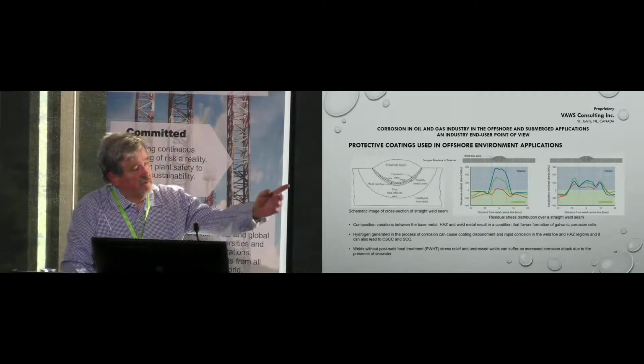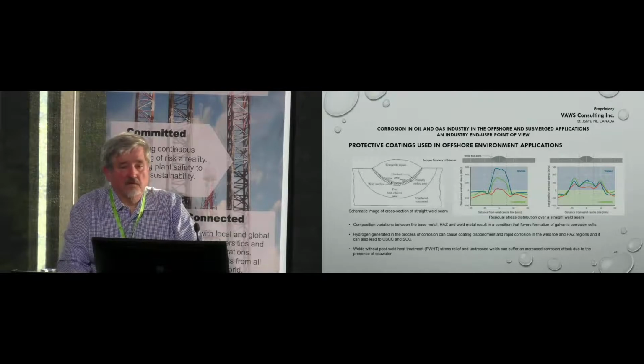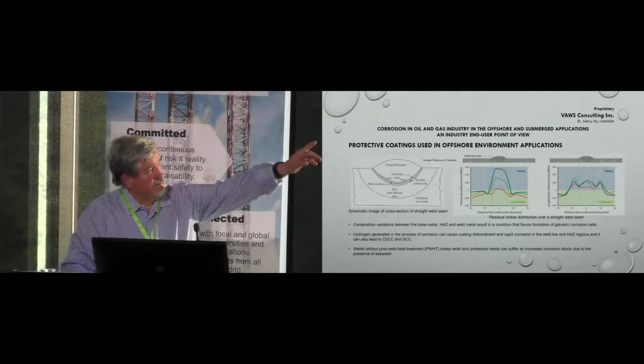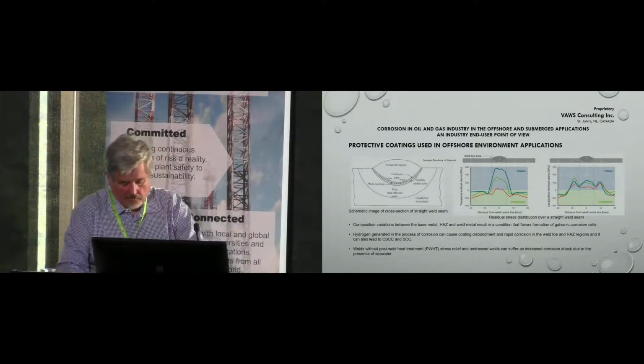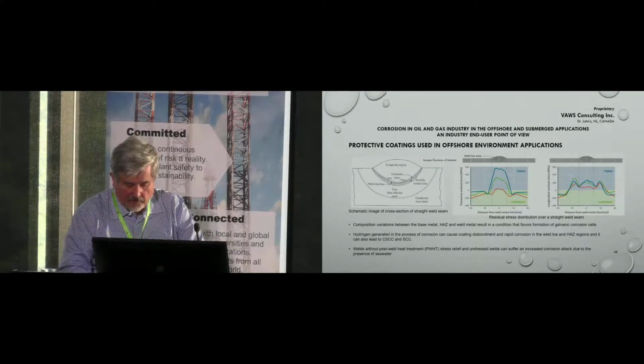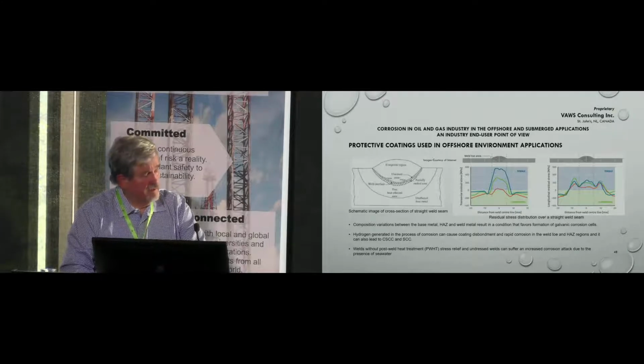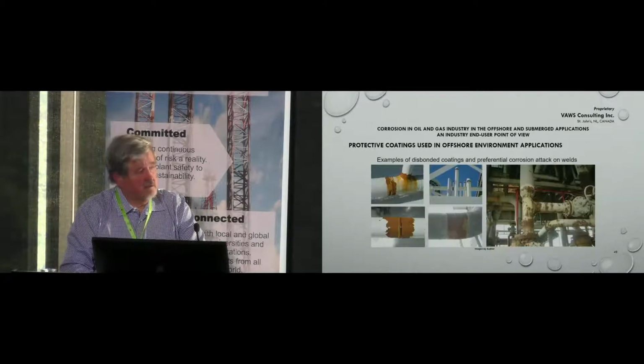And this problem with the welds was significant around the 50s when they were building icebreakers for Canada. And the icebreakers basically fell apart in the area where it was welded because of preferential corrosion in the toe of the weld. That's the transition between the cap and the horizontal metal. That's where the corrosion is usually the highest. And you develop grooves, deep grooves around the weld, and if you don't have enough material behind it, it can result in cracking. So it is very important to either select welding procedures which don't input too much heat, use proper welding materials, or use stress relieving and these kind of modern things.